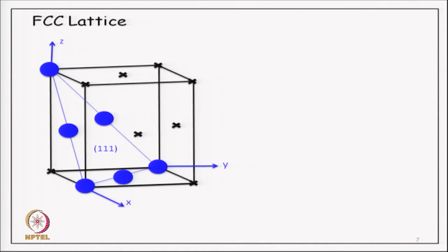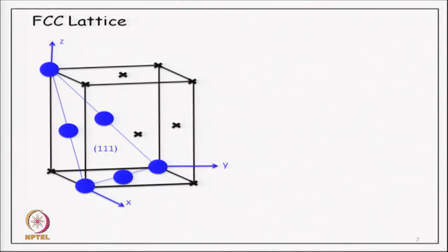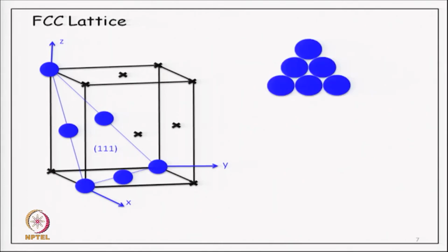If we let these atoms grow so that they touch along this closest direction, then the diameter of such atoms will be exactly half the face diagonal of the cube. So, if we place such atoms, of diameter half the face diagonal of the cube, at all of these sides, then we will get a stacking of atoms shown here.